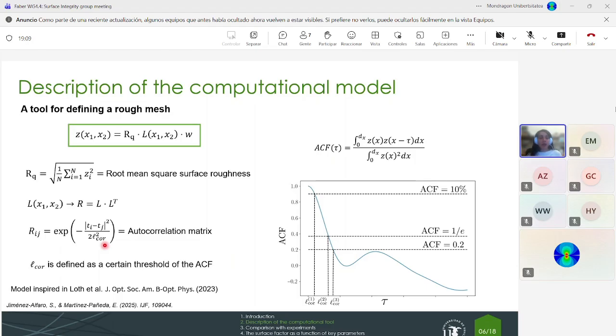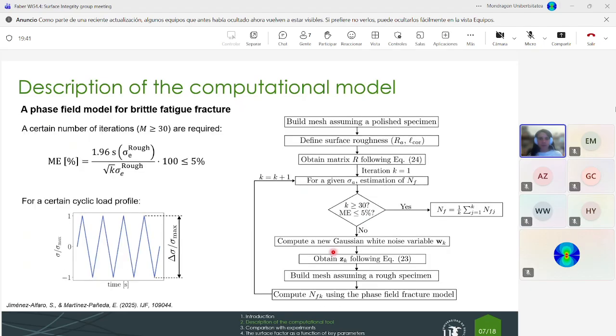And we have found that there are different proposals for defining this correlation length. In fact, we highlight three of them. They are related to when the ACF, the autocorrelation function, decays at 10%, when the ACF arrives at a value equal to 1 divided by e, where e is the Napier constant, or when ACF is equal to 0.2. So a part of our work is to use the three of them and to see which one gives better results if we compare to experiments.